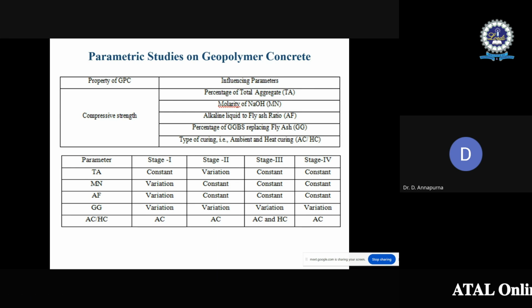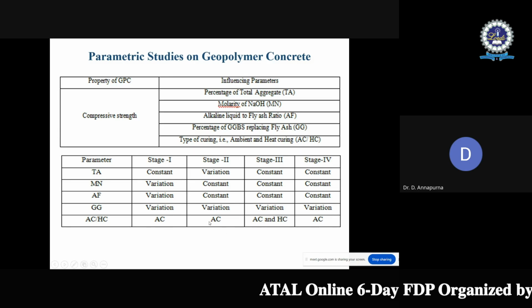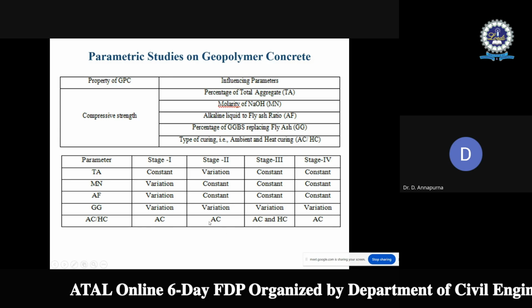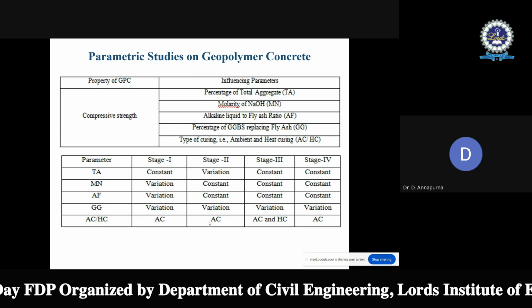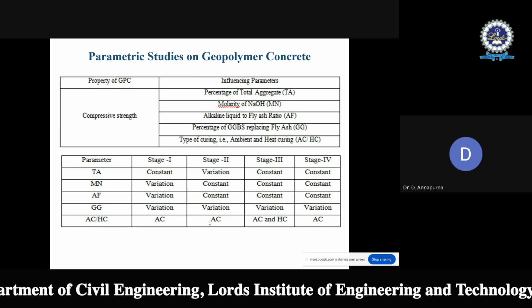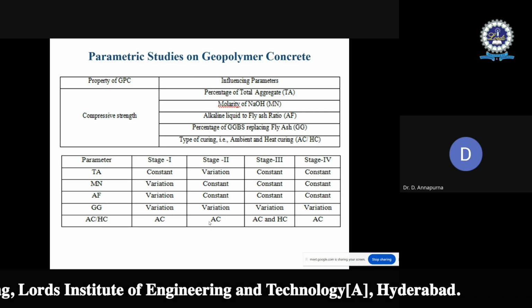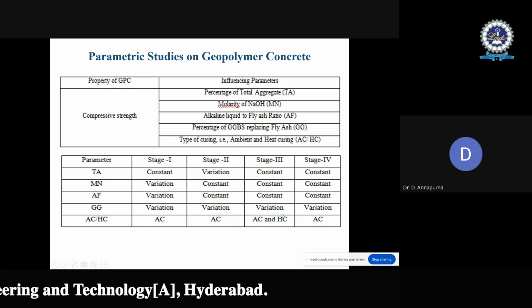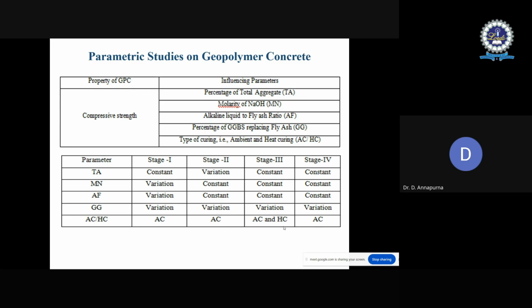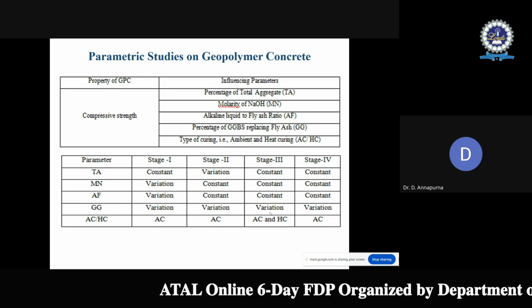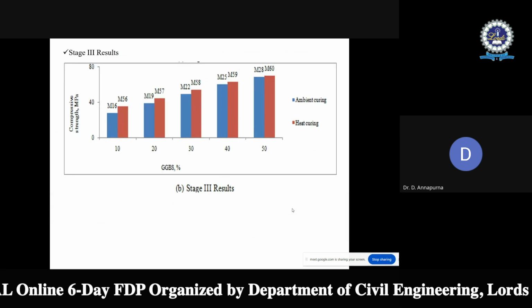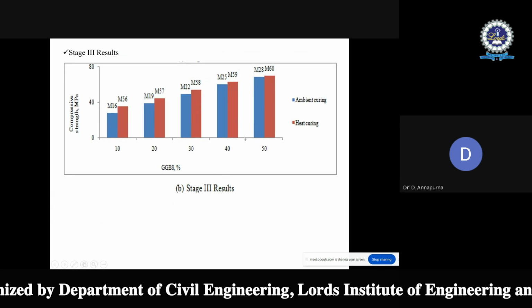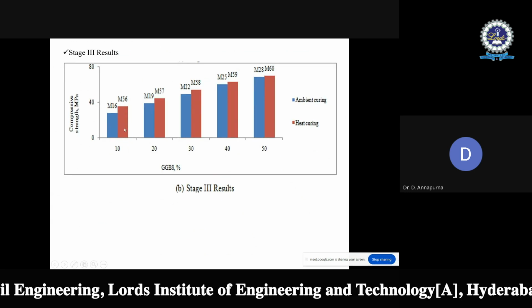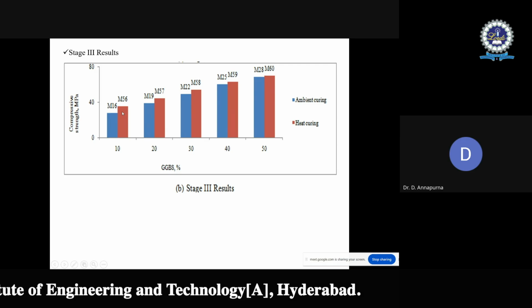Then comes the curing. In the earlier stages, only ambient curing was considered; the effect of curing was not considered. So here, both types of curing conditions are considered, heat curing and ambient curing. In the heat curing, the samples are cured in the oven at up to 60 degrees temperature for 1 day. The samples were again crushed for compressive strength, ambient curing was conducted as well, and the results were shown like this. If we check here, this red line indicates the heat curing.